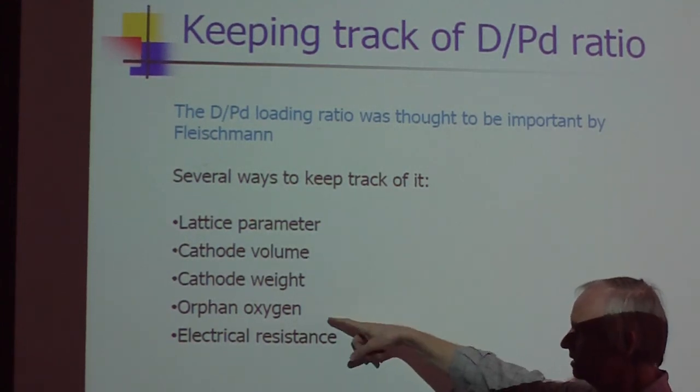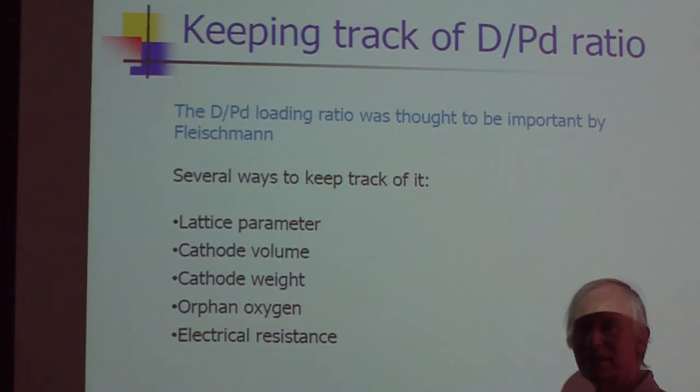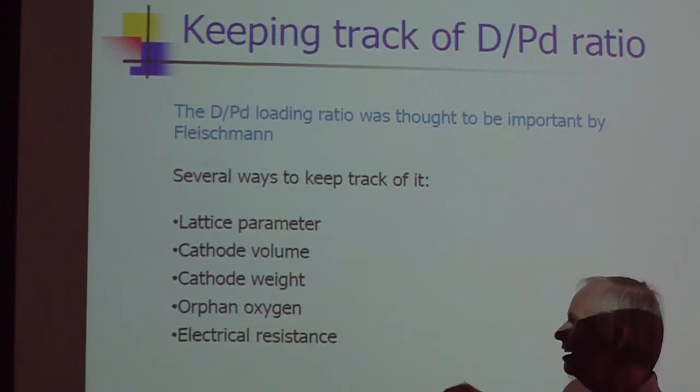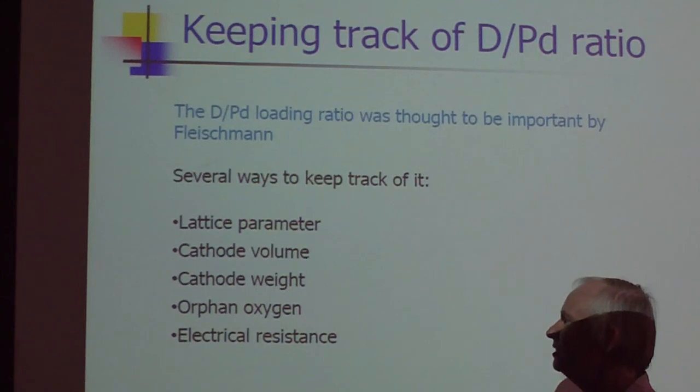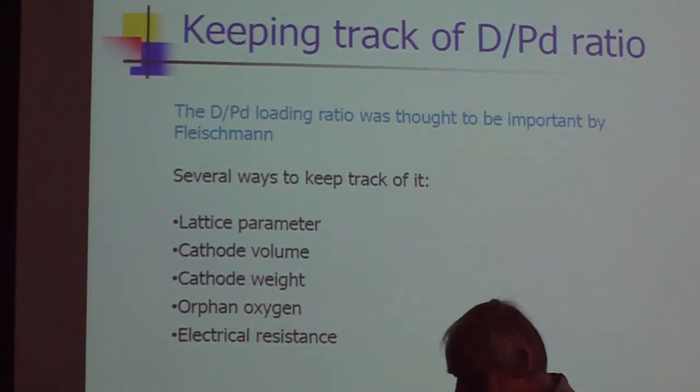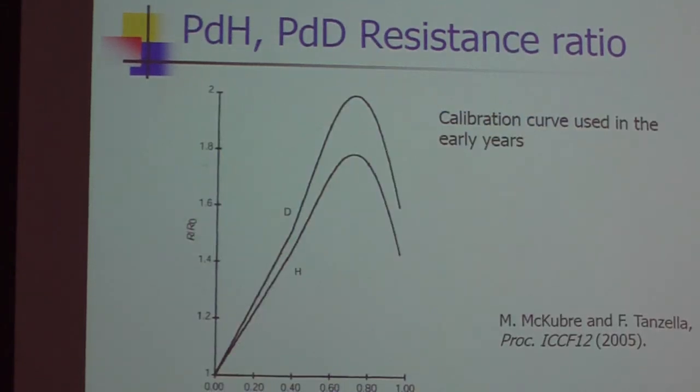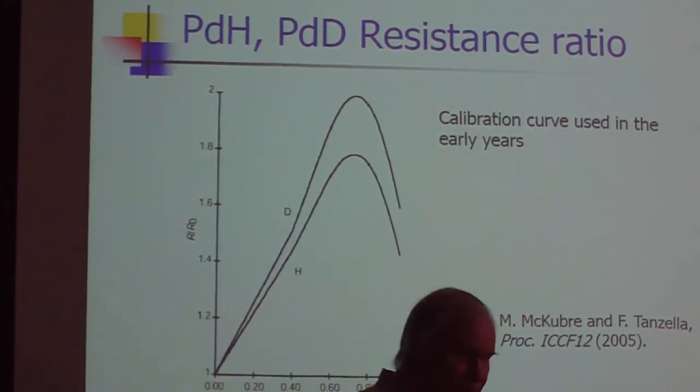The weight. And Storms measured oxygen from splitting the water—the deuterium goes in, the oxygen goes off. And if you measure the oxygen, it tells you something about the hydrogen deuterium. Electrical resistance. Well, in this field, the electrical resistance has tended to be the more important diagnostic for determining loading.